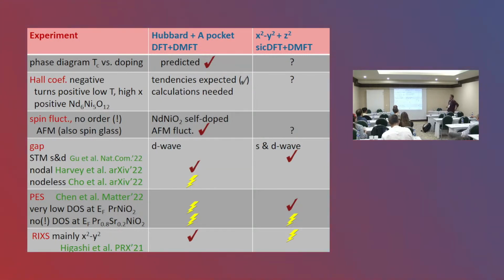And we predicted the phase diagram with astonishing accuracy. I already briefly mentioned the Hall coefficient, so at least the tendency is that it is positive for the 5-layer, and it is negative and only turns positive at low temperature and high doping for the infinite layer compound. That is what one would qualitatively expect, these tendencies, but we didn't do a calculation yet.